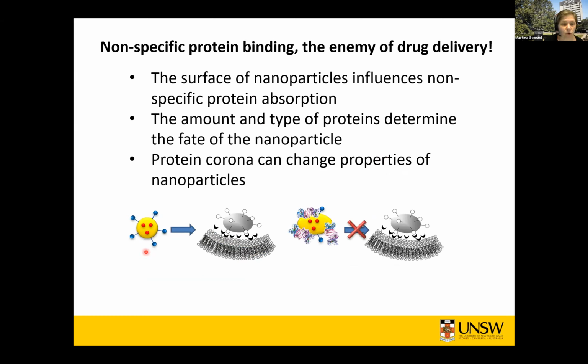So we started off with nanoparticles with fructose on the surface, expecting that these nanoparticles will interact with the cell membrane in a very specific manner. But what we found is that we actually have proteins on the surface that might really inhibit that specific uptake. So the surface of the nanoparticle influences non-specific protein absorption, and the amount and type of proteins determine very much the fate of nanoparticles. So now we have these proteins here, and then suddenly you might find that your nanoparticles are taken up by the immune system very quickly.